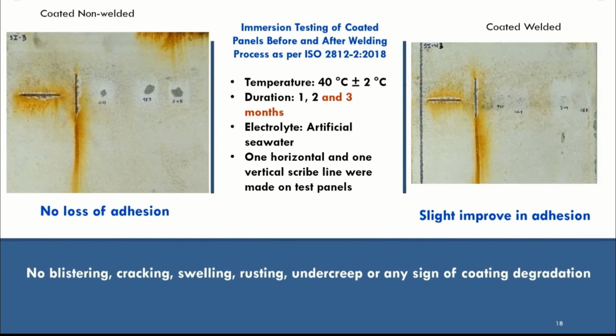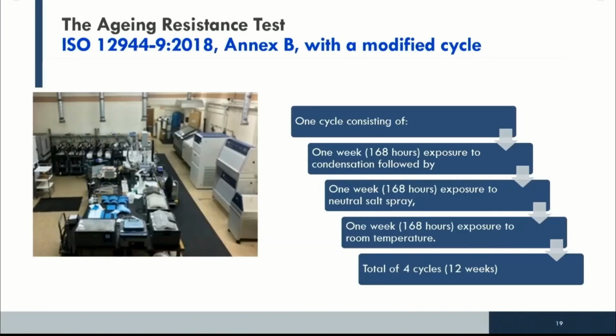The only thing we observed here is that for the coated welded one, we started with lower pull-off values than with the coated non-welded. However, within time, we found an improvement in the coating, in the pull-off value, and in the mode of failure. Initially, with no welding, the mode of failure was to the steel or to the alloying passive layer. However, after immersion testing, the pull-off adhesion strength has increased, and the mode of failure was cohesive within the ceramic layer. The second test we decided to do is an aging resistance test.